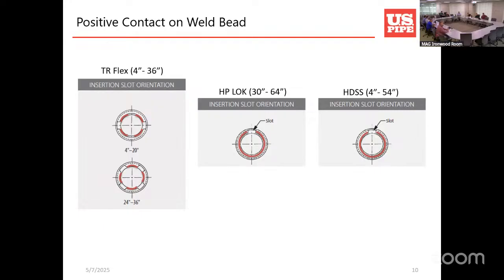The thing with the TR Flex is in the larger diameters, 30 and 36 in particular, under high pressure situations, since it doesn't have a contact area all the way around the circumference of the pipe, it creates these point loads, which is why we actually had to derate it by 100 PSI in 30 and 36 inches. What I mean by that is a class 350, which is normally rated at 350 PSI, was only rated at 250 PSI. So you had to use that class 350 pipe to get that 250 PSI rating. Sort of a limitation there. And then with the HP Lock, you almost have a full 360 degrees of contact area on that weld bead, which is why it had a higher pressure rating.